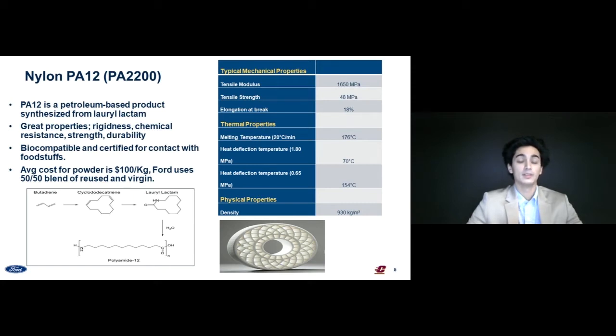The powder is roughly about $100 per kilogram, and Ford tries to reduce this cost by mixing it with reused powder, so that we have a 50-50 blend of reused and virgin powder. The reused powder comes from the old builds, and the powder that is unsintered and left on the top is brushed off and used to blend with the virgin powder.